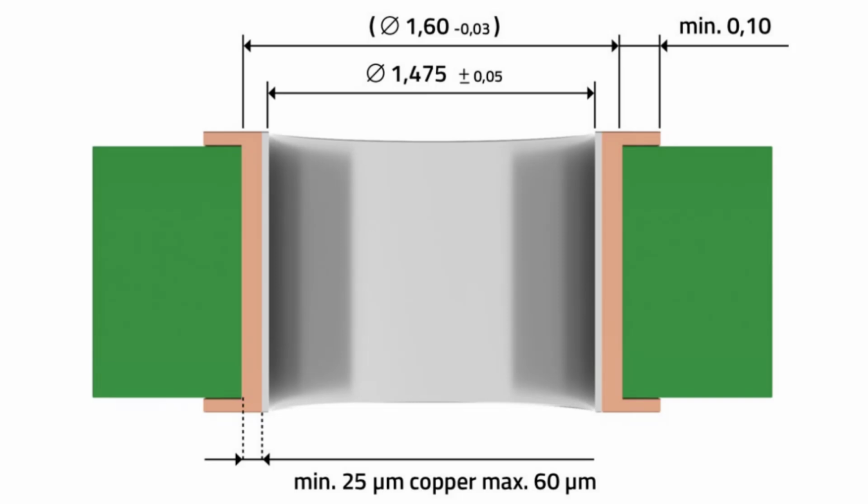This can lead to chip formation on the pin or to contact problems with the PCB in conjunction with the existing nickel layer. Now, on the other hand, immersion-coated PCB surface finishes ensure even distribution of tin throughout the via hole, and this makes it easier to meet tolerances and effectively prevents chip formation. Chips, plating, or solder push out of the via can actually affect the technical cleanliness of the system, and although rather unlikely, it could actually lead to short circuits as a conductive particle.